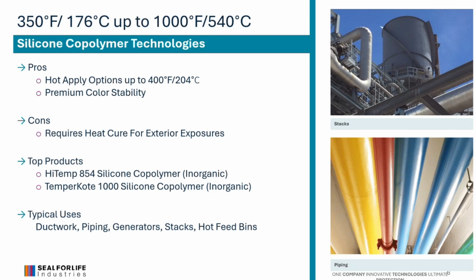Some cons, requires heat cure for exterior exposure. Our top products here are HiTemp 854 silicone copolymer and the TemperKote 1000 silicone copolymer. Standard uses are ductwork, piping, generators, stacks, and hot feed bins. And as you can see, there's a stack right up on the top right-hand corner and just some of the high heat piping that is color coded. Once again, this will hold these colors, even the safety colors, because of the way they're manufactured with dry grind pigments.